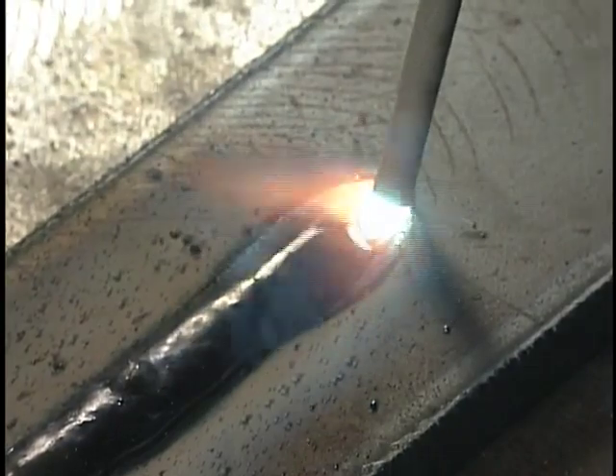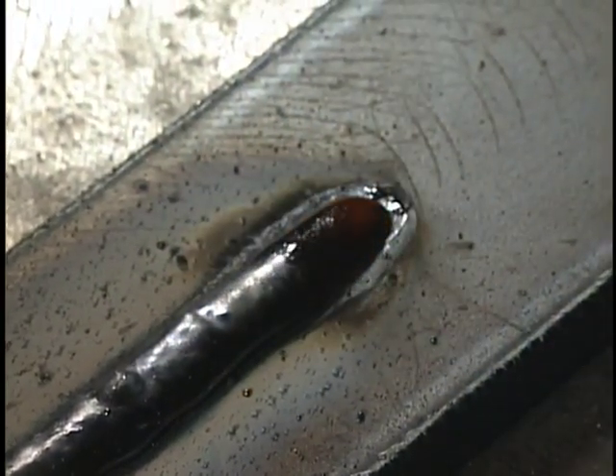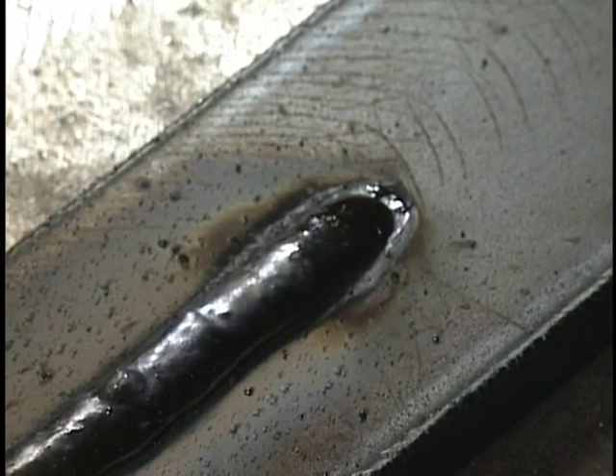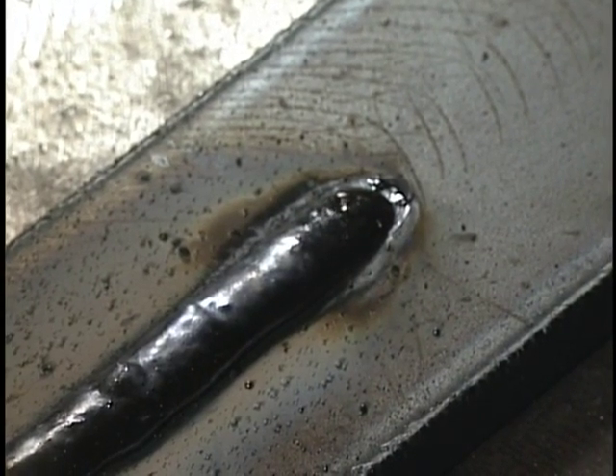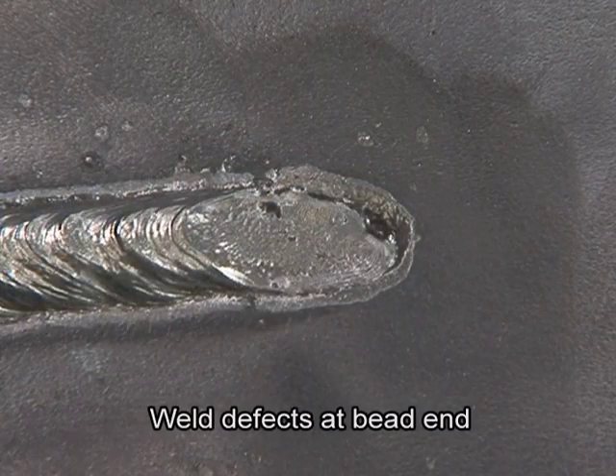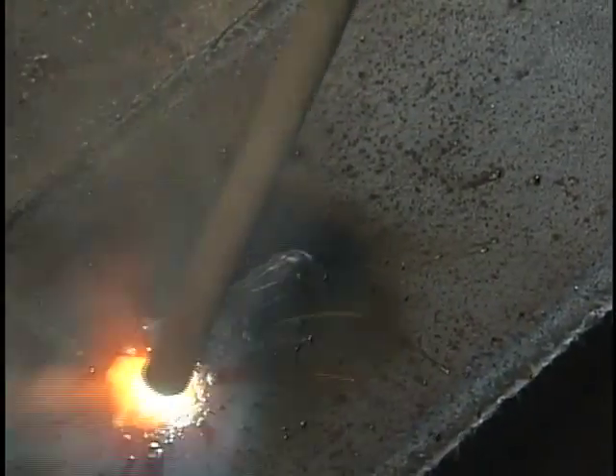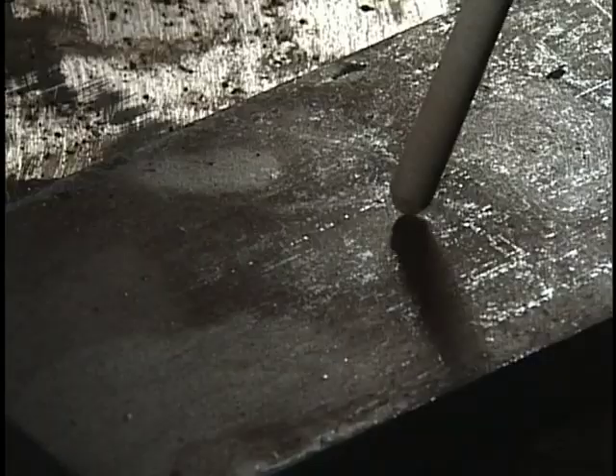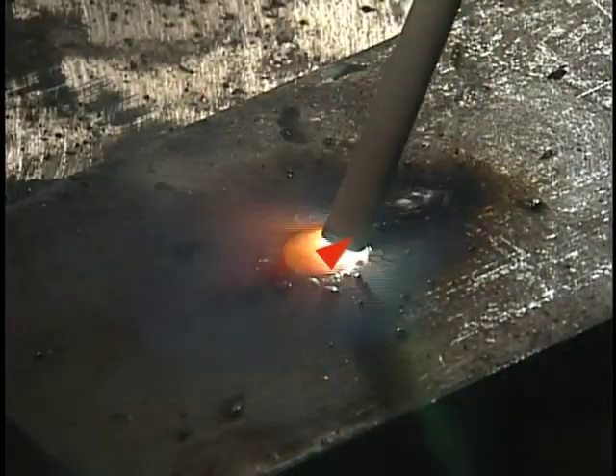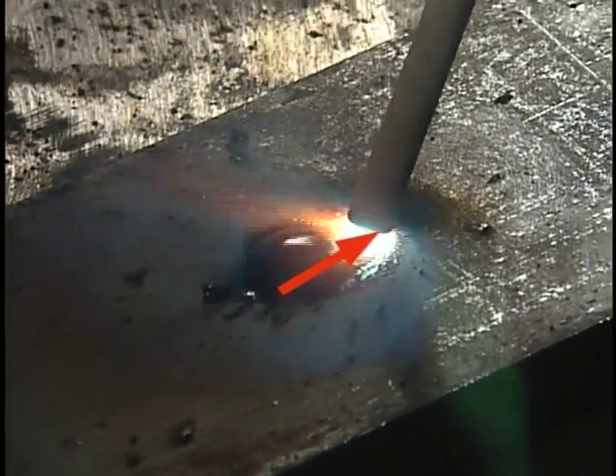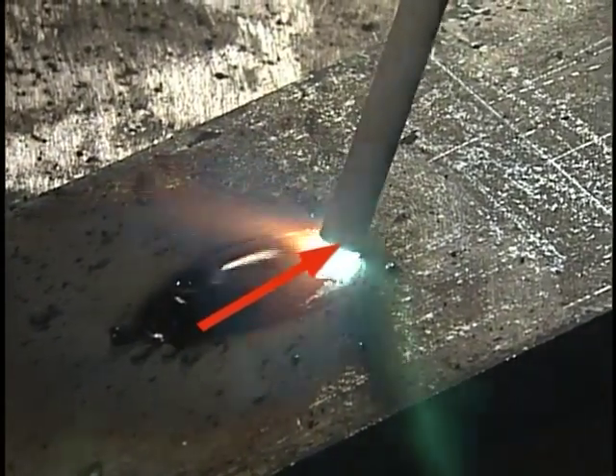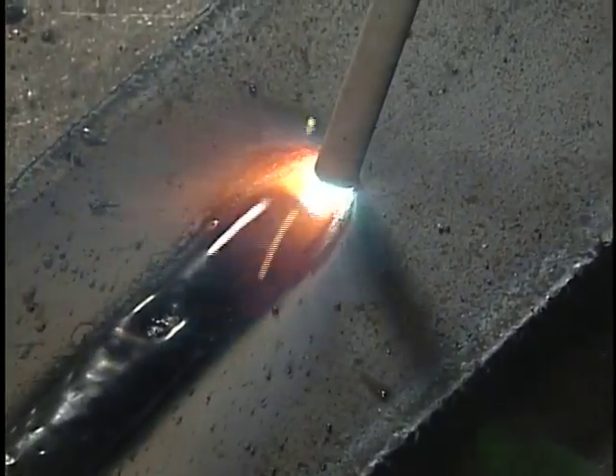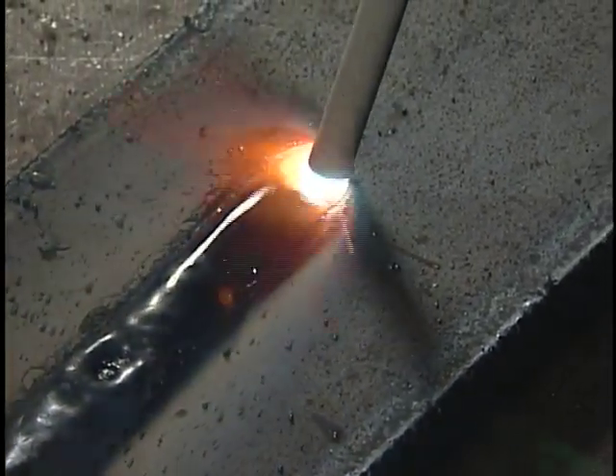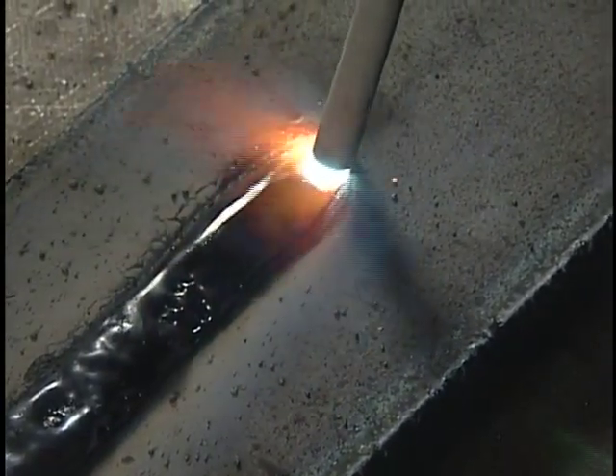Meanwhile, a cavity known as a crater is created if the arc is suddenly discontinued at the end point of the weld seam. Insufficient bead thickness and sudden cooling mean that craters are highly prone to cracking. Therefore, you must use the retract start technique at the bead start point to stabilize the arc. At the end of the bead, discontinue arcing after filling any craters by moving the welding rod as if you were drawing a circle.